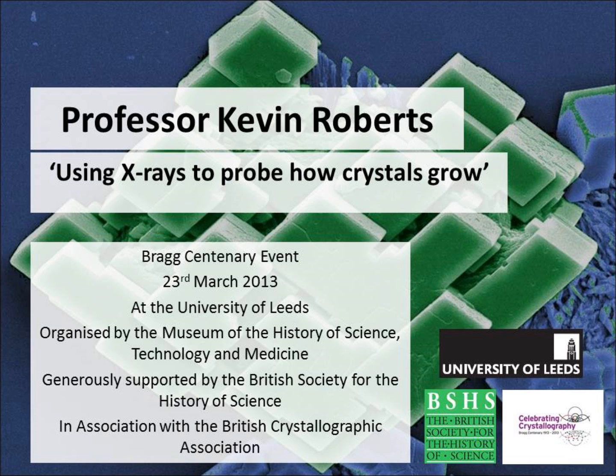But if we put inhibitors in them, we can transform, through molecular design, the crystals into not only tiny crystals, but also little equantly shaped ones. So we stop the crystal growth here, and we leave that one well alone. It's slow enough. And so you get a situation that if you have a pipeline like this, bang, fuel, that's how you can't start your diesel on a Saturday morning like today. And that's because my tank is full of little thin crystal plates of wax. I then put the additives into them, and they flow through nicely.